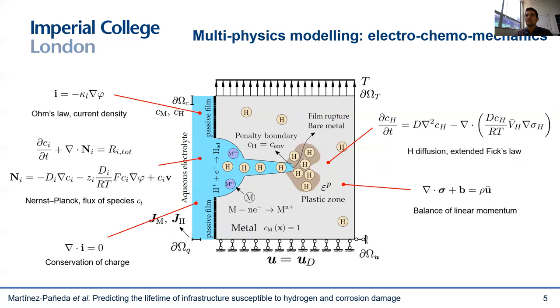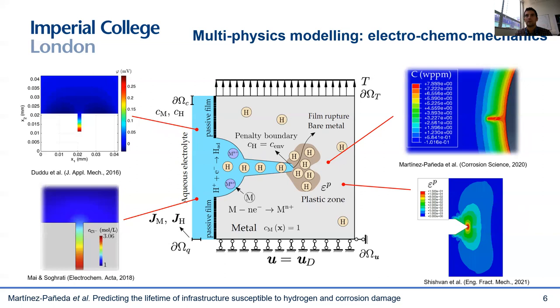The first one is multiphysics modeling. We know well the equations that describe those physical mechanisms, and we finally have enough computer power to solve them in a coupled fashion. We can predict the stress state in the material, the distribution of current, potential, and various ionic species in the electrolyte, the uptake and diffusion of hydrogen, and so on. So if we know the mechanisms and understand their interactions, we finally have enough computer power to resolve them explicitly from first principles.